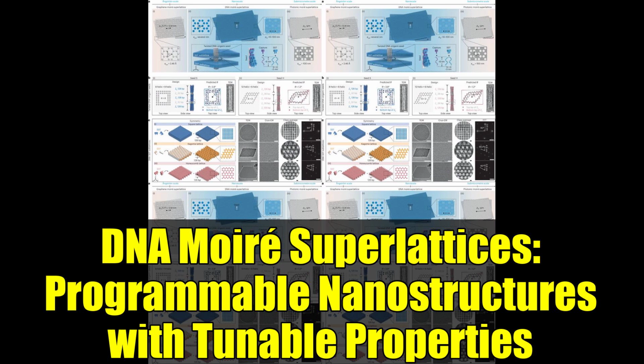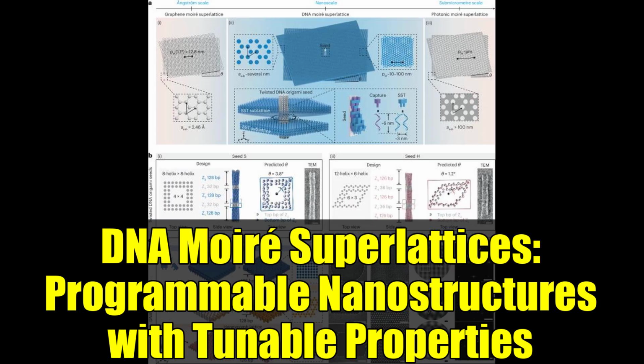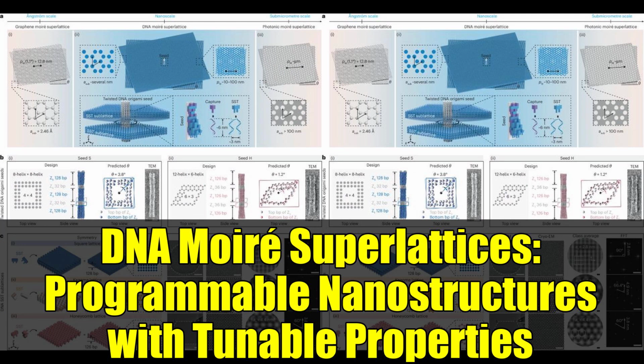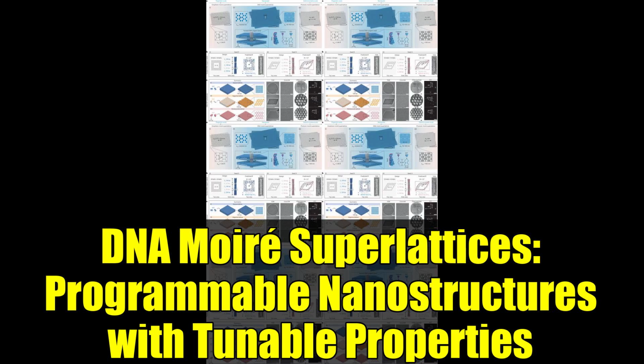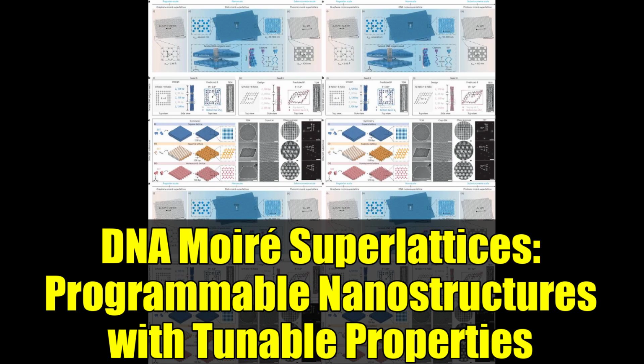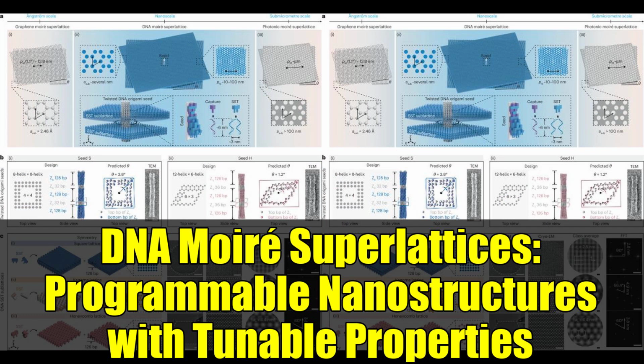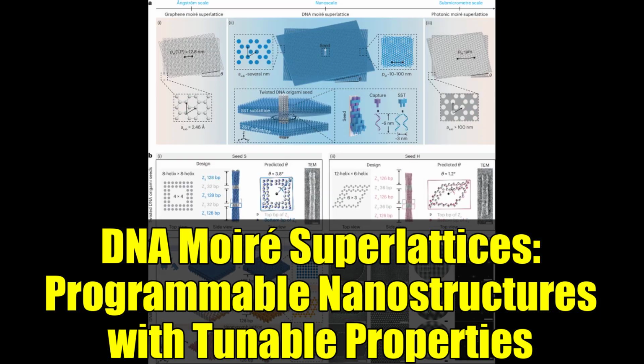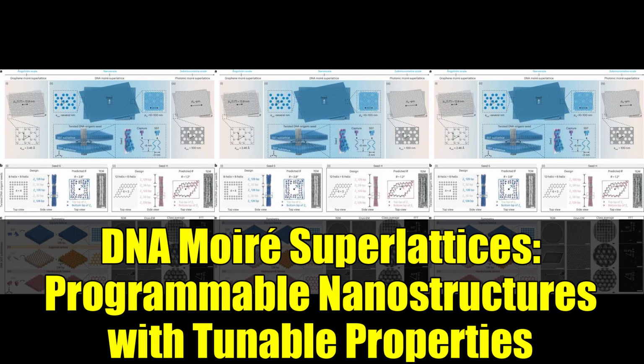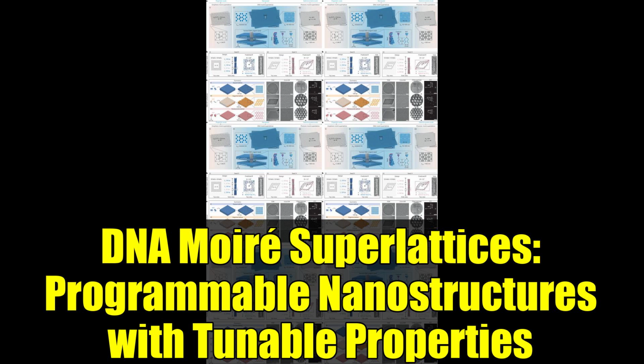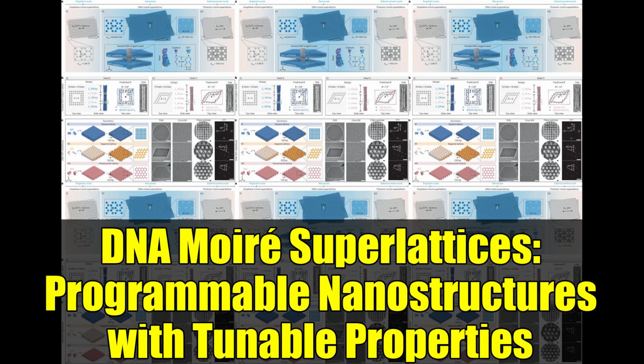As for the 2D DNA sublattices? By orchestrating DNA tile sequences and assembly conditions, the team built square, kagome, and honeycomb lattices, each with their hallmark symmetries. Intriguingly, the kagome lattice emerges by relieving strain within the square lattice, acting as a loosely packed square with characteristic voids. To the naked eye via microscopy, these lattices are sometimes distorted round, rhomboid, or irregular hexagons, reflecting the stresses of dense DNA packing, but at their core, their atomic scale regularity shines through, especially in ultra-high resolution, cryo-EM images. But achieving these intricate Moiré lattices isn't just about making the right building blocks.